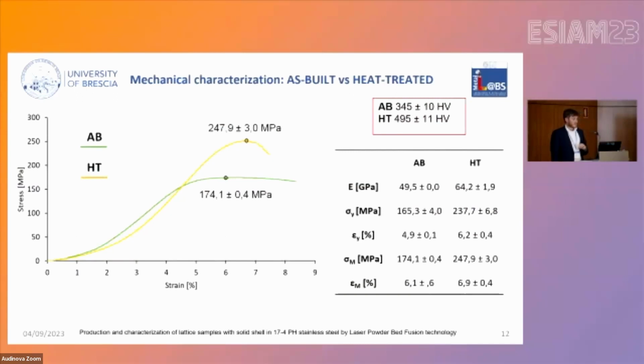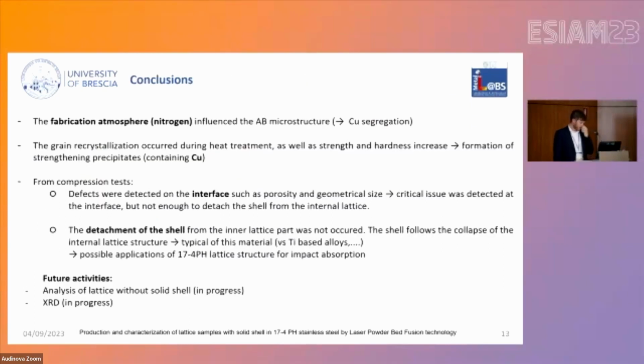Moreover, I also detected the hardness of the component. So we performed some micro Vickers hardness tests to understand if we effectively have an increase of hardness. And in fact, we detected an increase in the hardness for the heat-treated sample. This is probably due to the transformation of the microstructure, and also to the presence of precipitates. Moreover, I also collected some mechanical results about the Young's modulus, yield strength, and ultimate strength, and we found an increase of the resistance and also of the hardness.